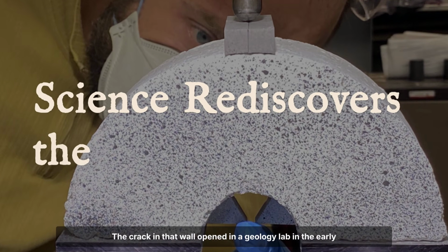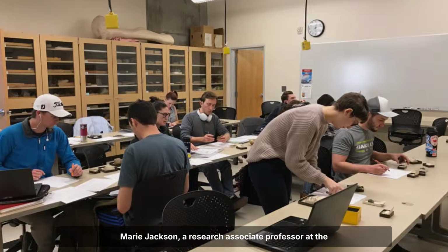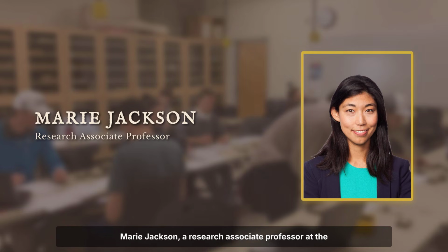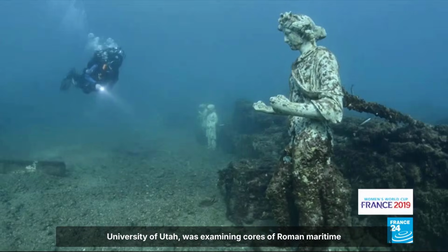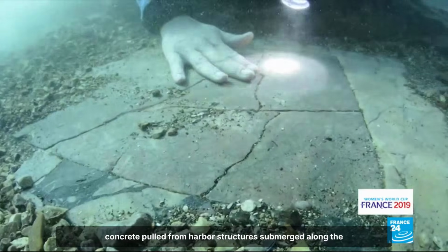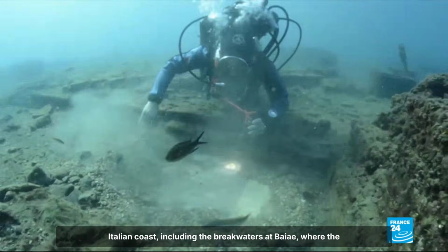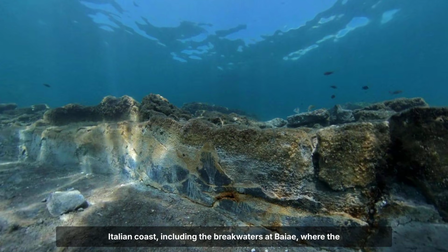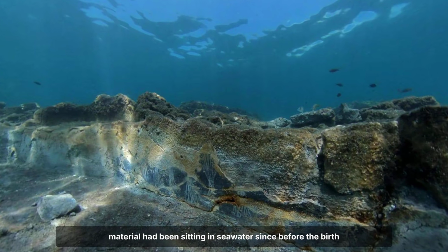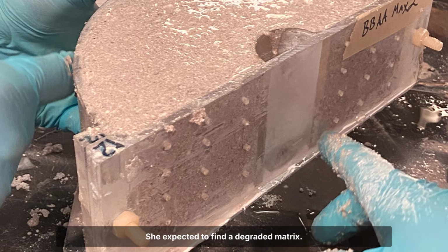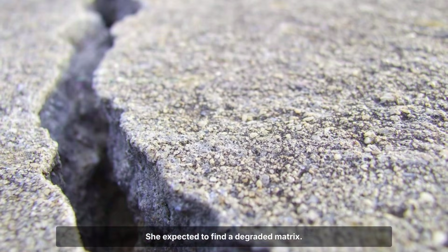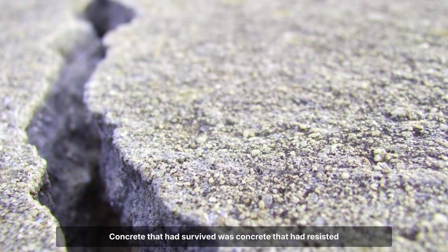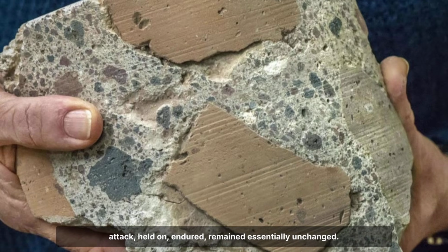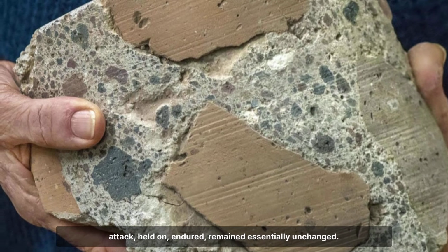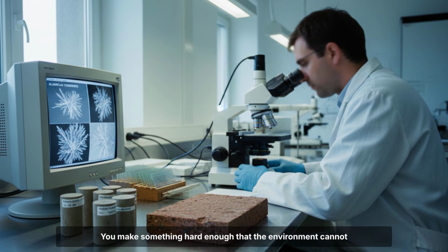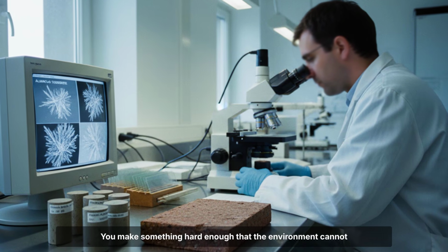The crack in that wall opened in a geology lab in the early 2000s. Marie Jackson, a research associate professor at the University of Utah, was examining cores of Roman maritime concrete pulled from harbour structures submerged along the Italian coast, including the breakwaters at Baiae, where the material had been sitting in seawater since before the birth of Augustus. She expected to find a degraded matrix. Concrete that had survived was concrete that had resisted attack, held on, endured, remained essentially unchanged. That is how durable materials work. You make something hard enough that the environment cannot break it down.